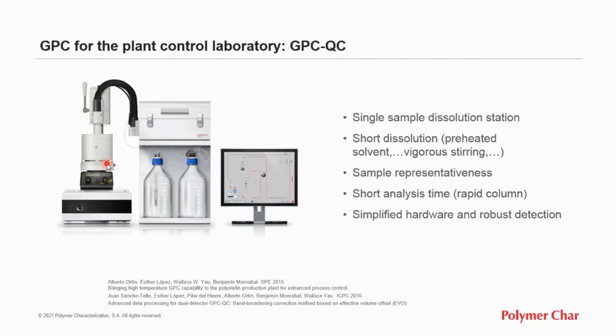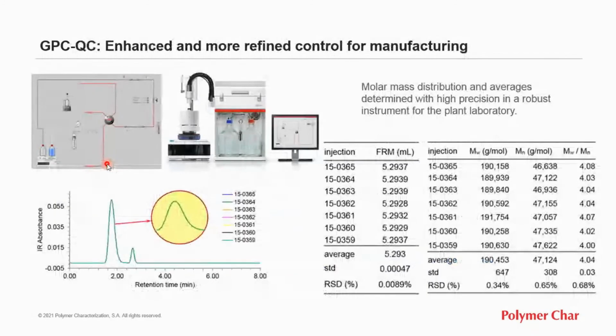Following this workflow, the GPC QC can be operated continuously with a cycle time of 1 hour or less, which is found appropriate for controlling the startup of reactors or when a change of grade is conducted. Once the process is stable, production may need to be controlled at a slower pace, maybe once or several times per day.